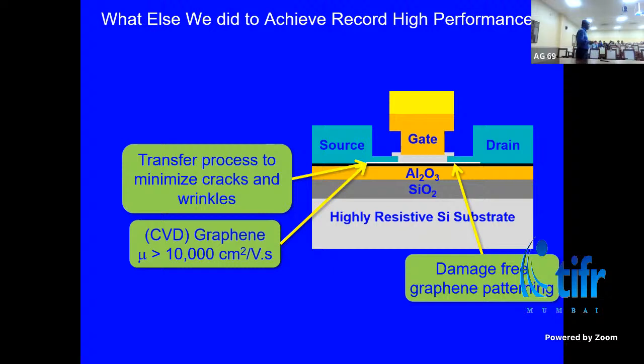The other issue is, how do you pattern? When you pattern, you use photoresist to block certain regions and pattern. Now, a lot of these photoresists have affinity towards this pi bond, right? And if they have affinity towards the pi bond, it would be very difficult to take them out. Either they will tear graphene or they will peel off graphene. After it is patterned, it's basically present in the form of small islands, so it's very easy to peel it off from the substrate. So how do you deal with that? We developed this process which was damage-free graphene, and that's why you see the previous picture, which is very clean islands of graphene, and that's what you get quite repeatedly.